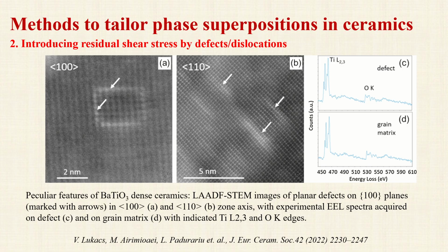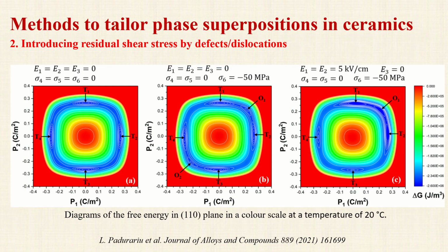Another method is to intentionally introduce local stress or strain, preferably shear stress, by defects or dislocations, as we recently presented in this work. One major advantage of Landau-Devonshire theory is that it can take into consideration the role of local stress, as shown in literature before and by us in a recent paper. The application of a moderate shear stress favors a stable and well-defined minimum of energy in orthorhombic phase. In addition, the orthorhombic phase formation can be further facilitated by the application of an external electric field.